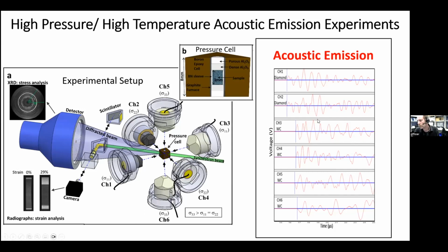And we also, on the back of the anvils, have piezoelectric transducers, which convert mechanical vibrations into voltages. So then we can measure any acoustic signals that are generated in the sample with these piezoelectric transducers. And this is just showing an example of an acoustic emission.